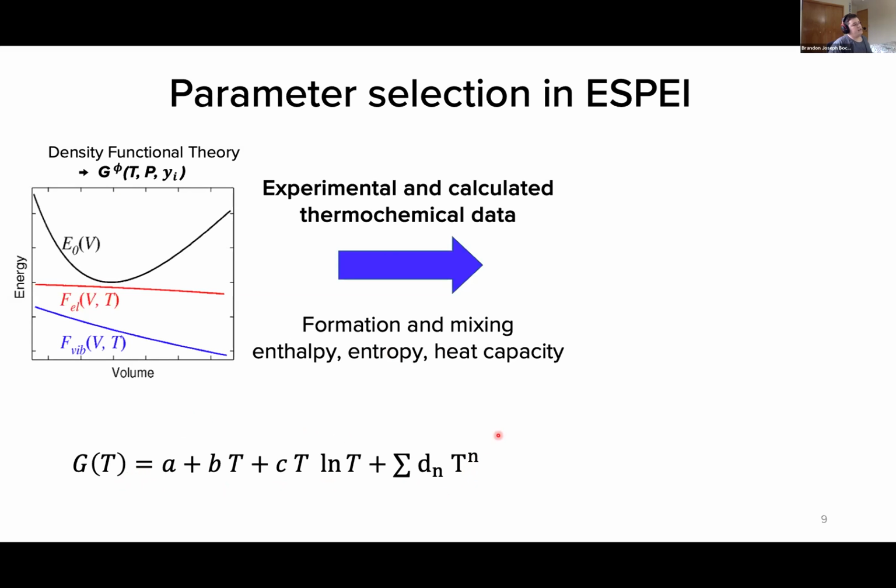If we just naively apply this to a set of Gibbs energy data or data that have all the derivatives, we might vastly overfit our Gibbs energies. So maybe we'll fit 5 or 6 coefficients to fit the data exactly. But of course, as many of us know, having a more complex model leads to overfitting and can lead to poor predictions and poor extrapolations.